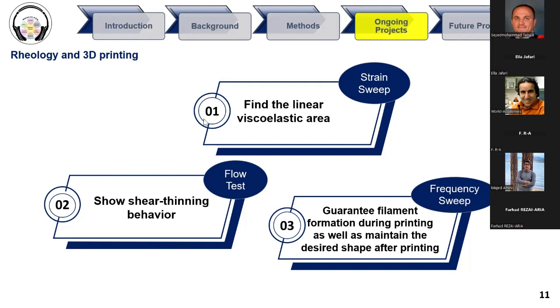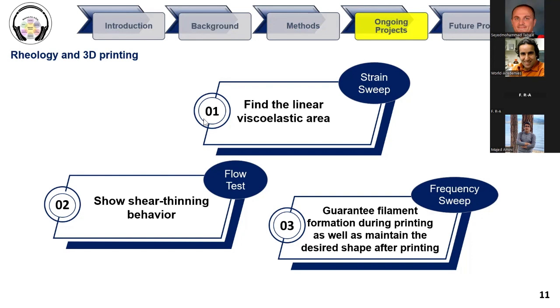It means that whenever we increase the shear rate, the viscosity should decrease. Also, to make sure that we have filament formation during printing, and that we have the desired shape after printing, we need to conduct a frequency sweep, and we need to evaluate the loss and storage modulus, G double prime versus G prime, and let's see what happened. Actually, in my last work, I correlated rheological properties with the printing quality quantitatively, and I will explain how we can quantitatively correlate these two important concepts.